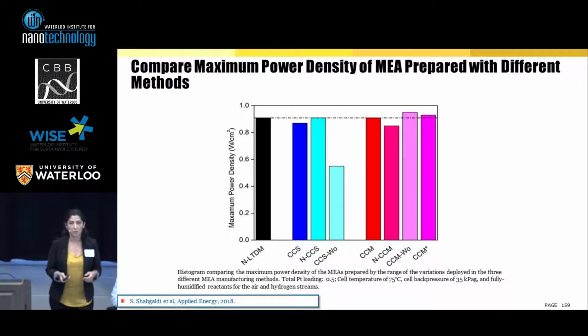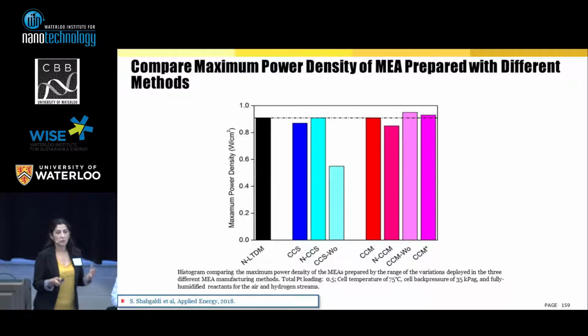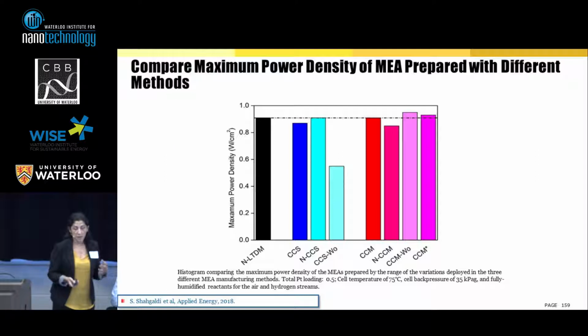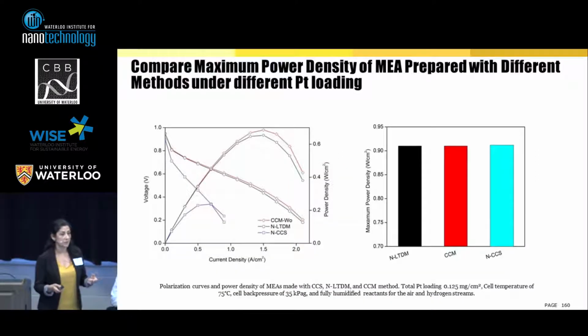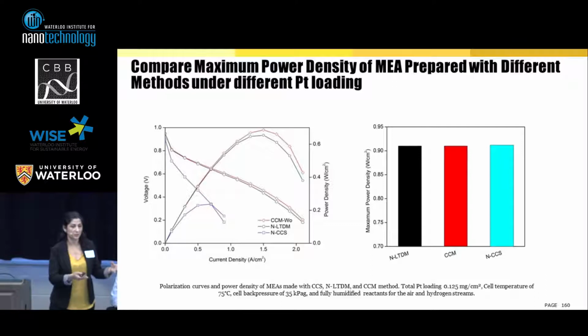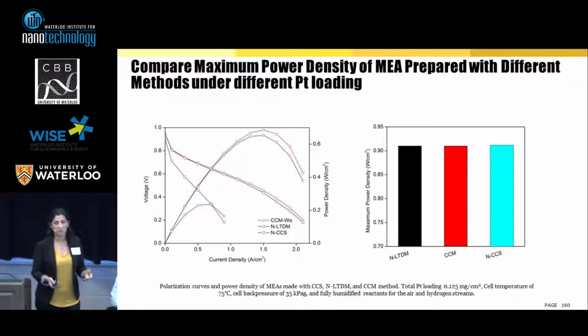This is some results that I want to share with you. We found that no matter what kind of method we are using, with a little bit of modification of each, we can reach the maximum power density if we have high platinum loading. I mean, if we have enough catalyst to react in our reaction, okay? But if you go through the literature, you will find a lot of discrepancies in the results. We found that these discrepancies come from the amount of platinum or catalyst the people are using. That's why some groups say this method is better, and others go with the CCS or CCM method. We found that if we bring down the platinum loading to 0.125, the CCS method, for example, here, shows the lowest performance. However, in the same condition, when we have high platinum loading, we get the exact same performance.